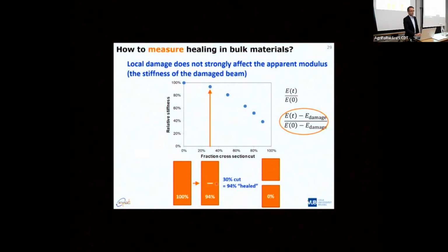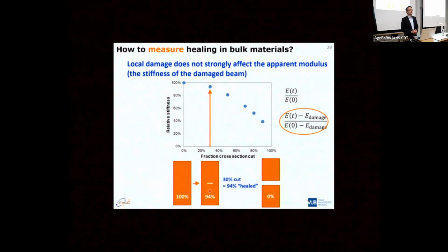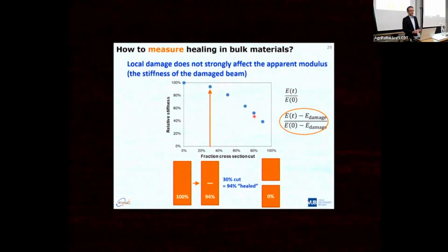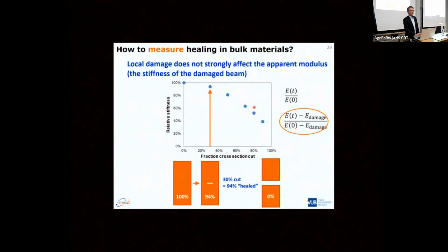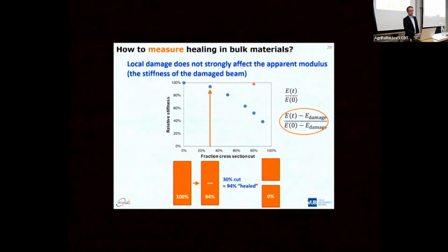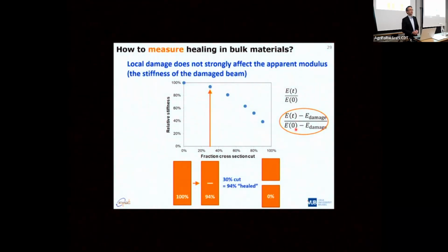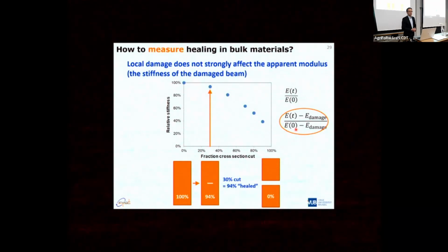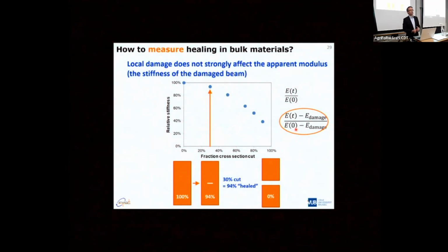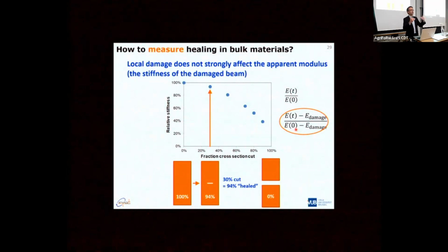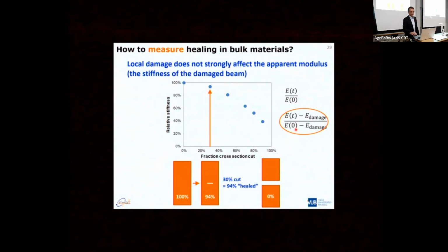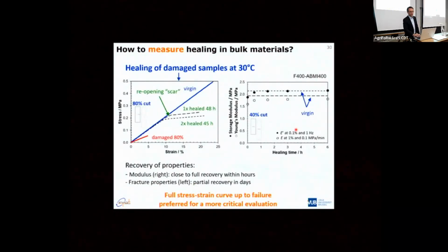Of course, if you start from this state, you cut it 30% or you cut it 80%, you start somewhere here. And then you look at how that modulus is recovering, and you use the relative evaluation with respect to the property after the damage that you applied. Then, of course, you get a much better measure of how your crack plane, your cut plane, is healing. When you purely look at the modulus, you also miss a lot of information.